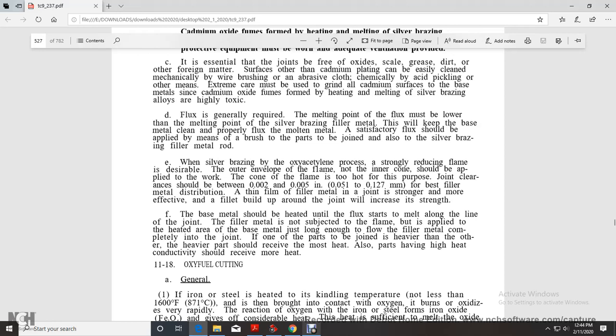The flux should be applied by brushing the parts to be joined, but can also be applied using the silver brazing filler metal rod. The joint clearance should be at least 0.002 to 0.005 inches for best filler metal distribution.